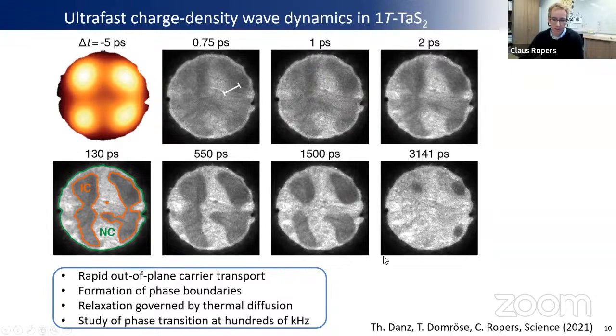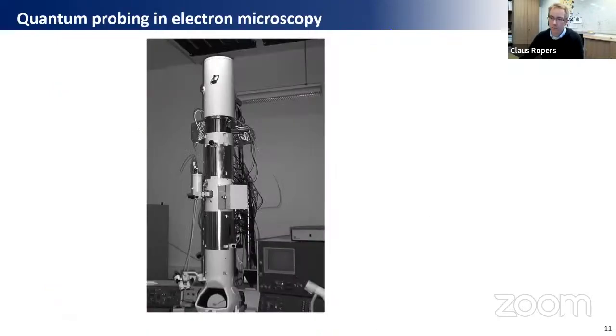So what we can extract from this, if you want to take a closer look at this data here, is essentially formation of phase boundaries and then slow relaxation back to the original phase over timescales of several hundred picoseconds. Okay, so that was basically the example I wanted to show on structural dynamics probed in this ultrafast TEM.